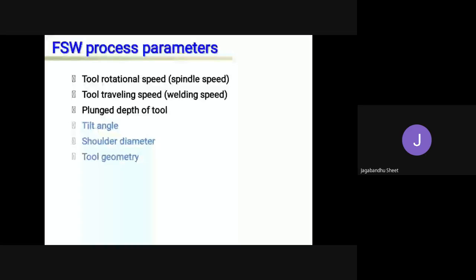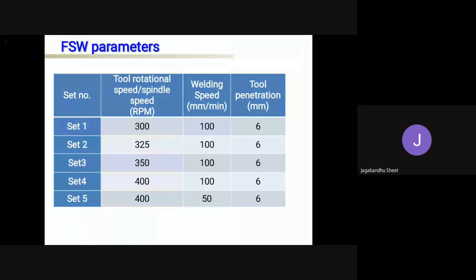So this is the process parameters involved in friction stir welding. We have worked on the first three process parameters, that is tool rotational speed, tool traveling speed, and the plunge depth. The first set of process parameters was 300 rpm, 100 millimeter per minute welding speed, and 6 millimeter penetration depth. This 6 millimeter penetration depth has been kept constant for all sets of process parameters, and the rotational speed is varied from 300 to 400 rpm, and the welding speed is varied from 50 to 100 millimeter per minute.